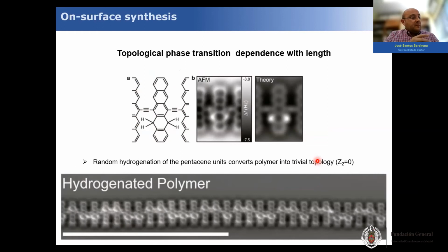In a further development of these experiments, we observed previously that some of the molecules of the Pentacene polymers were shorter than the larger ones, and the shorter ones weren't non-trivial. So we decided to run an experiment, taking long polymers and hydrogenating them by introducing atomic hydrogen into the microscope chamber. As you can see here, it randomly hydrogenates.